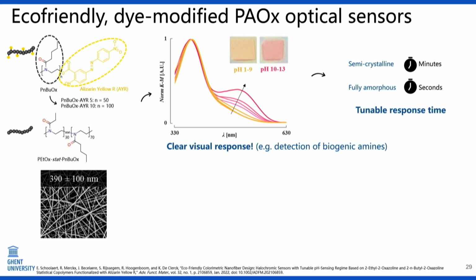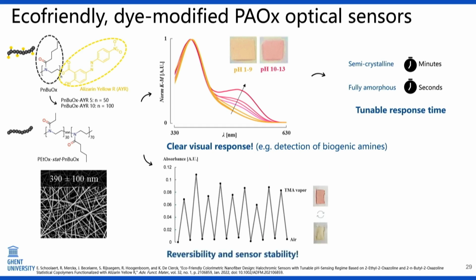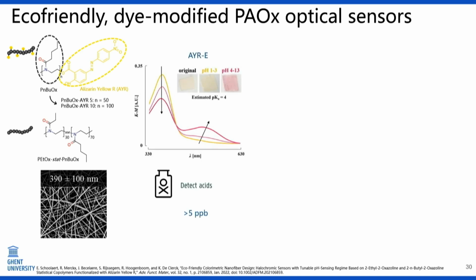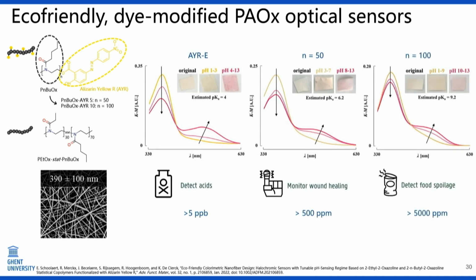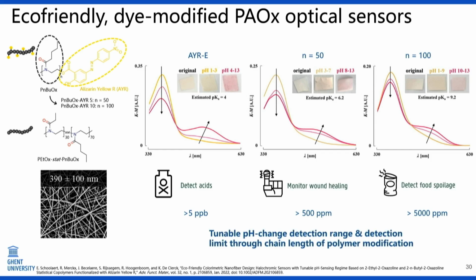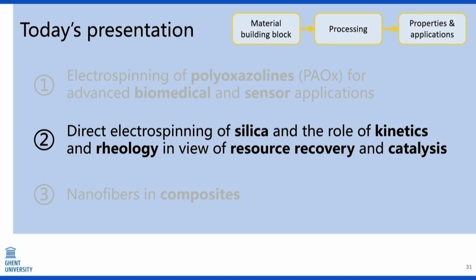Minutes has the advantage of a much longer readout time, which could be important for some applications. Seconds give an immediate response, but a lower readout time. The sensors were reversible and stable. And as said, by tuning the length of this PEtOx chain, we could tune the pKa value and go for different applications, from detection of acids over monitoring wound healing, all the way to food spoilage detection. So by changing that length, we could tune the pH change and detection limit. These are two important applications that we used for our first platform of building blocks, polyoxazolines.